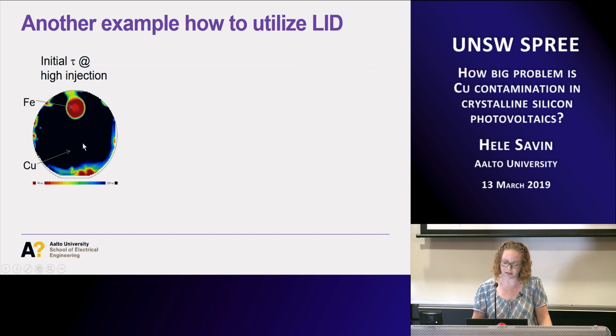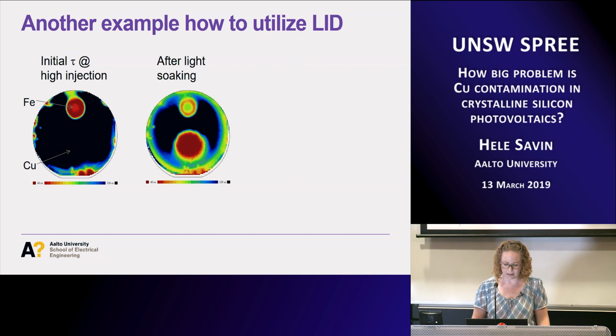We have also placed copper here. You measure the lifetime, and it looks perfect. You have milliseconds of lifetime. You could say, oh, we don't have any copper problem. But then when you shine light on this, for instance doing iron-boron breaking, you see that the copper degradation actually takes place, and you can reveal how bad the copper contamination is.